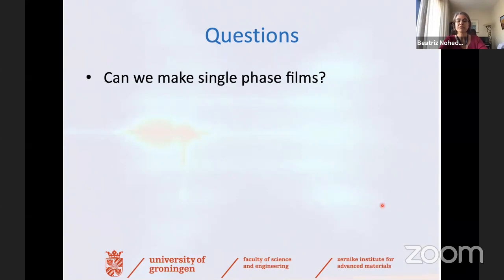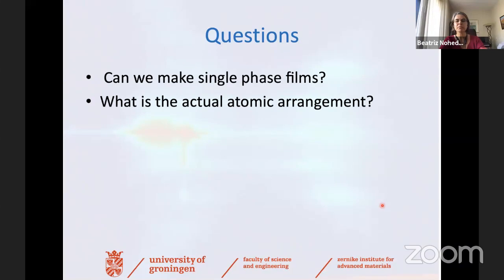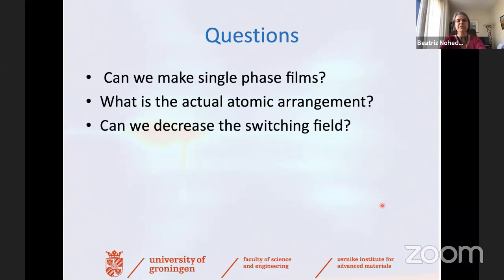So the functionality of the films was not optimal. What is the actual atomic arrangement? Because these films are polycrystalline and mixed phase, and very, very thin, it is very difficult to actually learn or do proper structural characterization and look at this exact atomic arrangement.